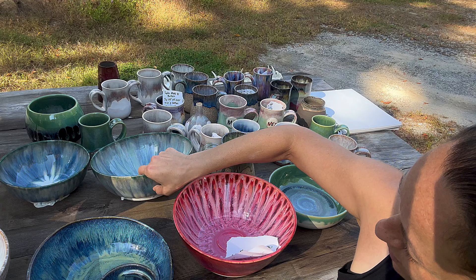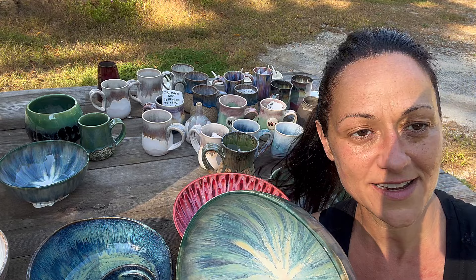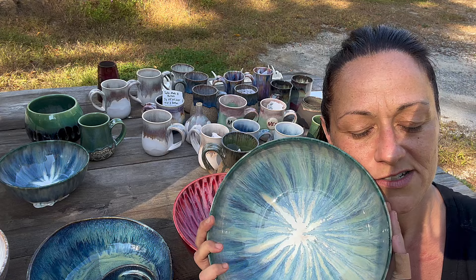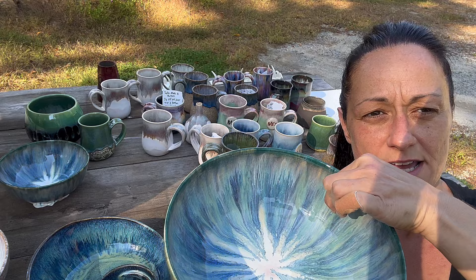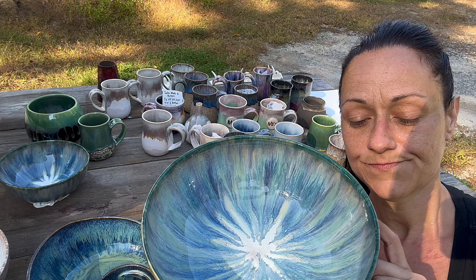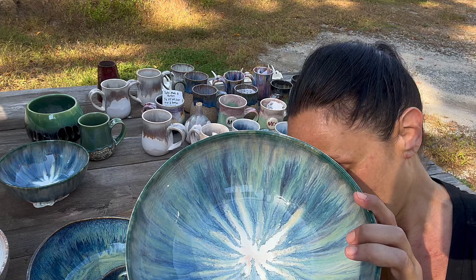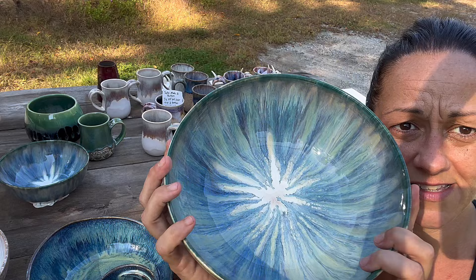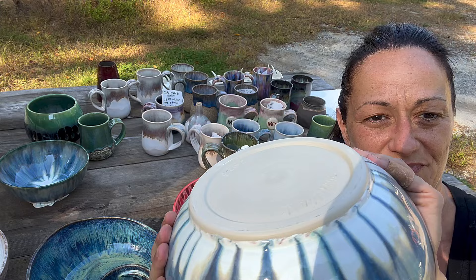This is a combo I use quite a bit, but I knew not to use Soft White — and I did it anyway. I went lighter on the bottom and it still didn't prevent running. Soft White as a base three times by Spectrum, then two times Power Turquoise, then two times Blue Rutile in stripe swatches, then two times Seaweed swatches, and a band of Flux. It was really close to the shelf — Matt's gonna have to do some grinding.